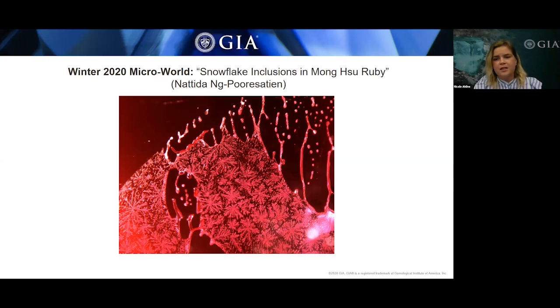So the Bangkok laboratory recently examined a 0.79 carat sugarloaf cabochon ruby. Gemological observations with chemical analysis indicated the origin of the ruby to be Mong Hsu, and while observing the stone under microscopic examination with a combination of dark field and fiber optic illumination, an open fissure with a snowflake-like pattern, as you can see here, from that flux residue was documented. This pattern is formed by the crystallization or devitrification of that glassy flux residue. And this partially healed fissure resembling these beautiful snowflakes is the first such feature the author has encountered in a flux heated ruby.